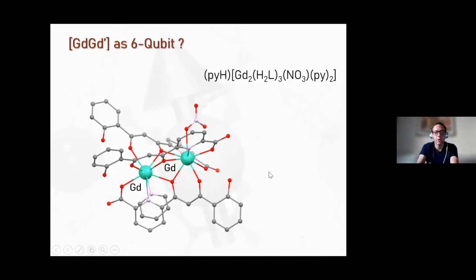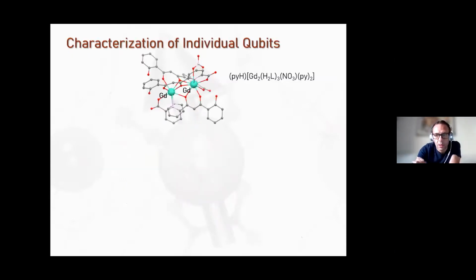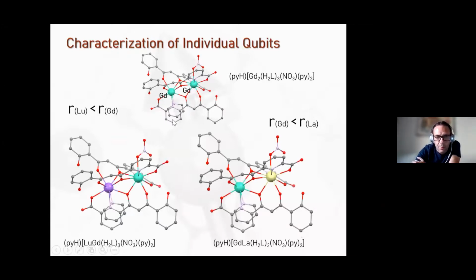So here we go back to our gadolinium system, a candidate for a 6-qubit system. What we did is to take this compound we have published already and try to study it in detail to see whether we can promote that as a 6-qubit quantum gate, or a 6-qubit system in one molecule. We took advantage of the versatility I mentioned before, which would allow us to study individually each gadolinium ion if we make the corresponding compound which on the other side has a diamagnetic metal. So for example, to study gadolinium in this position, we made a compound which has here lutetium, which is the place for the small metal.